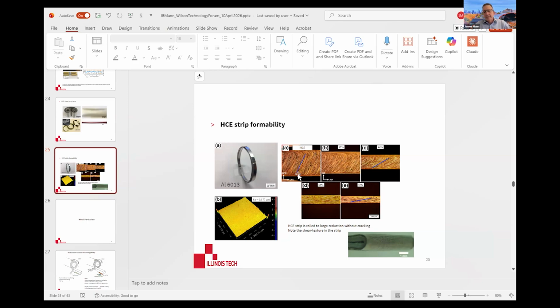And I don't have the pictures here to show you, but by imposing different conditions of the position of the constraint tool, we can actually create different hydrostatic stress states. And it can actually change how consistent it is across the thickness. But this shows an example of it being generally consistent, not 100%, but at the strip edges, there's a little bit of a difference in shear flow.